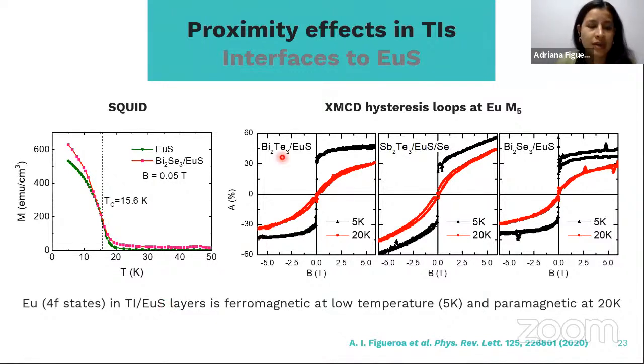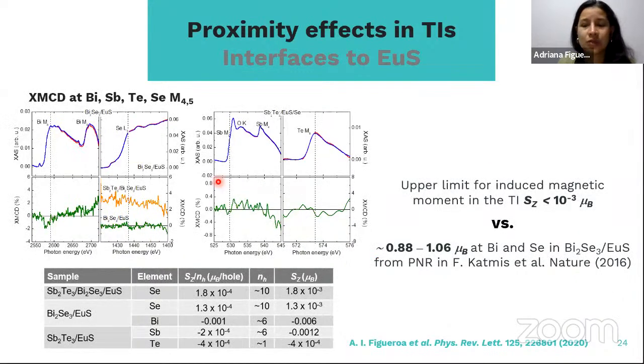Well, we don't see that. We measure both in SQUID magnetometry and with XMCD hysteresis loops, and we observe that at 5 Kelvin, these layers are ferromagnetic, and then they are paramagnetic at 20 Kelvin already. And this matches well, it agrees well with the Curie temperature observed for single layers of europium sulfide. So no changes in the Curie temperature because of the interface with the TI.